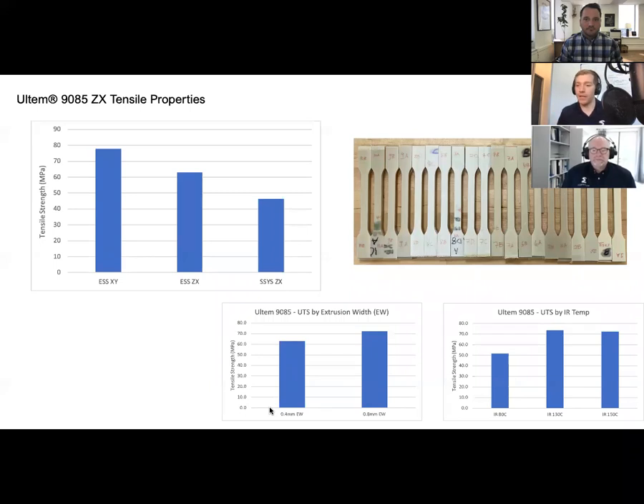For comparison, we pulled specimens printed with the exact same settings in terms of nozzle diameter and the size of the tower that we routed the Z dog bones out of. The Stratasys specimens were pulling in the mid to high 40 megapascal range, which is quite a bit lower. What I don't have on here, but can share, is that the standard deviations were quite a bit higher on the Stratasys platform because it has to pause, do some wipes, and come back over to restart. With the HSC, we don't have to do those things. We just blow right through the part at 300 millimeters per second for this print, and saw some really incredible values. If you're printing really big parts and can get away with a 0.8 nozzle, we've seen values in the low 70s, with very tight standard deviations on those parts.